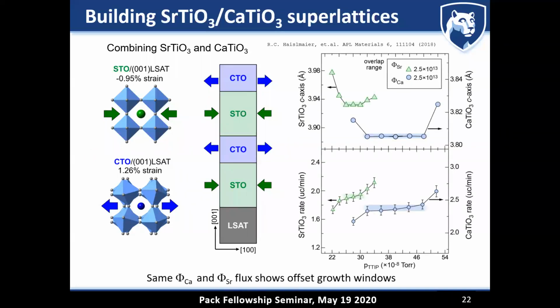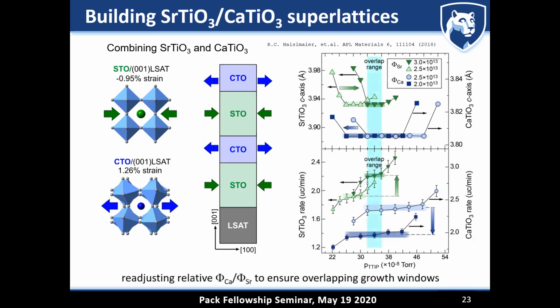Now, when we started to attempt this, we realized that, like in the case of calcium titanate, where we had a self-regulated growth window, which is shown here, we also find a self-regulated growth window for strontium titanate. You can see here the plot of the out-of-plane lattice parameter as a function of the metal organic flux. And the interesting thing is that the self-regulated growth window here for strontium is somewhat shifted relative to calcium titanate. And so what we did was we just adjusted the strontium and the calcium fluxes to make these two growth windows overlap. And it turns out that this is relatively easy. And as soon as you're able to control the position of these growth windows and you can line them up, you should be able, pretty much for the first time, to grow oxide heterostructures with controlled stoichiometry throughout the entire